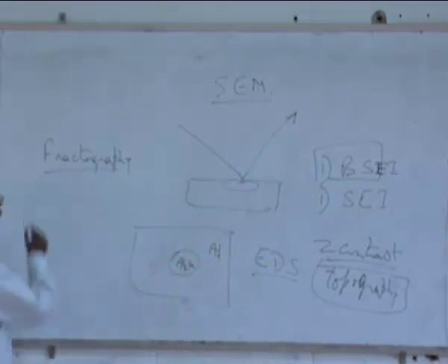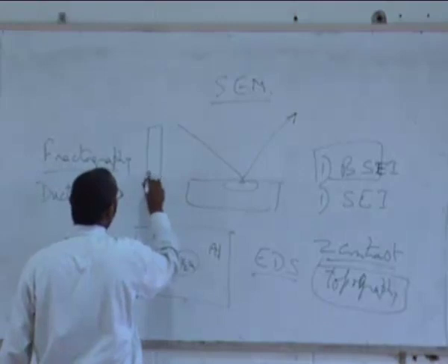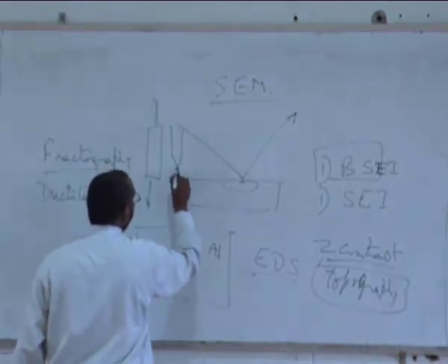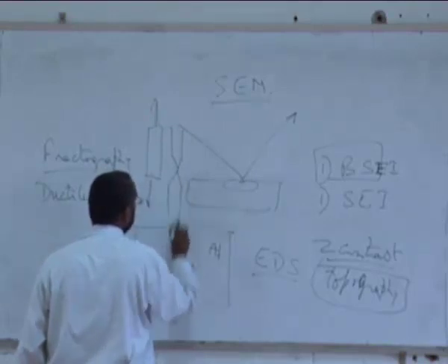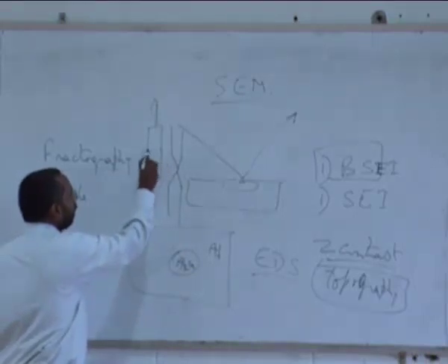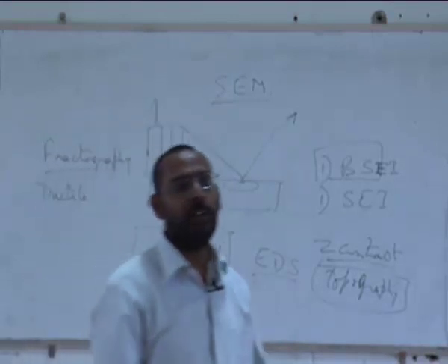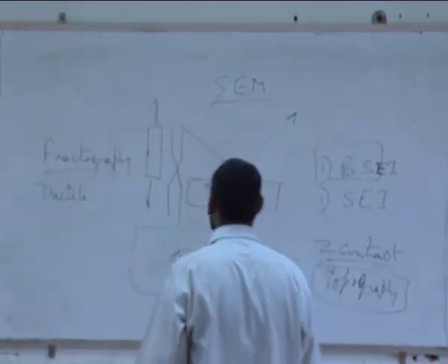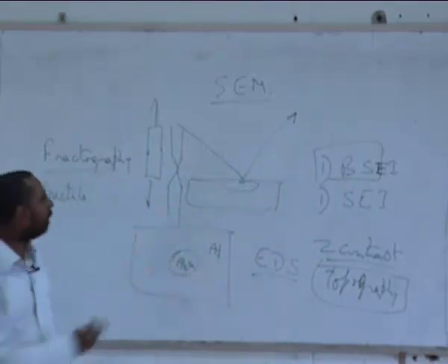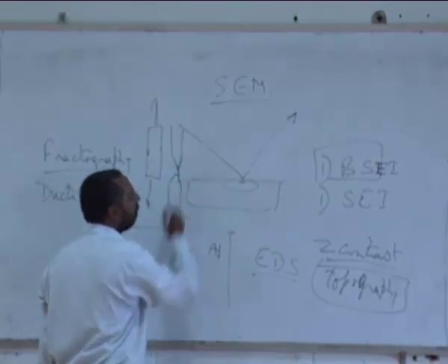and that can give you a variety of information. For example, if your sample is a ductile sample, usually if you take a rod like this and subject it to tensile loading, the rod will finally fracture like this. Because at some point the cross section starts decreasing at the center, and finally it will break. This is usually called a cup and cone fracture, if you have heard of this. So it will have something like a small cup, and this is like a cone fracture.